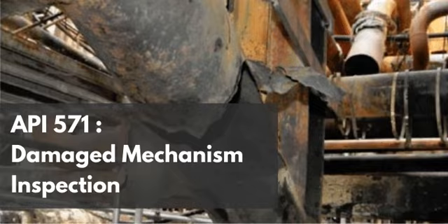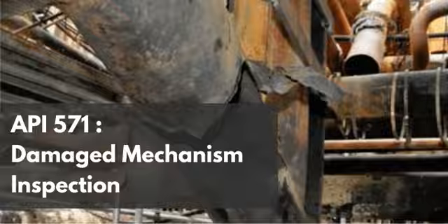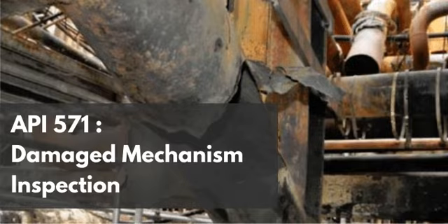The steel under the band expands drastically due to the heat, while the steel just an inch away remains cold and rigid. So when the heating band is turned off, the localized heated zone tries to contract, but the adjacent cold metal fights it. You successfully relax the stress at the weld, but you permanently locked in a massive new ring of tensile residual stress right at the boundary of the heating zone. You just moved the Amine SCC initiation site an inch to the left.